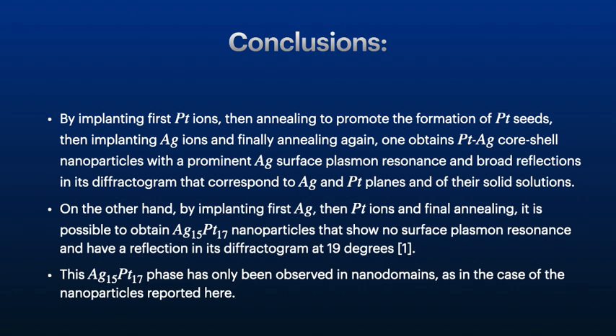phase in the nanoparticles dominates, and the absorption spectrum exhibits no significant plasmon resonance. At the same time, the X-ray diffractogram shows a reflection of the large interplanar distance present in this phase. This Ag15Pt17 phase has only been observed in nanodomains, as in the case of the nanoparticles reported here. Combining and optimizing the previous structures by varying intermediate implantation and annealing parameters is possible.